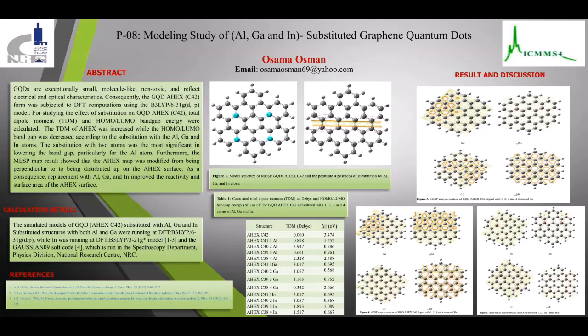Density functional theory was used to calculate the total dipole moment, the highest occupied molecular orbital and lowest unoccupied molecular orbital bandgap energy, and the molecular electrostatic potential. The basis sets employed in the model structure were 6-31G(d,p) for aluminum, gallium, and indium, and B3LYP 3-21G for aluminum.